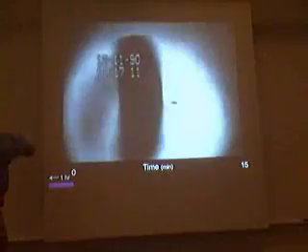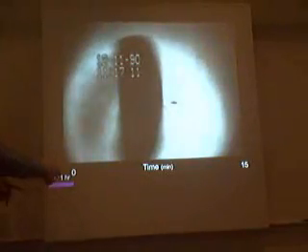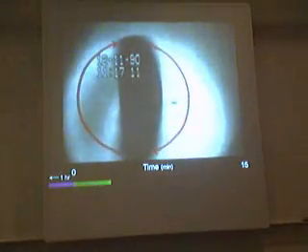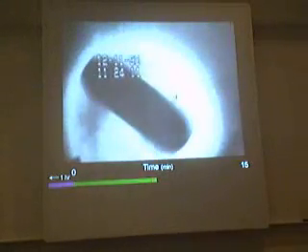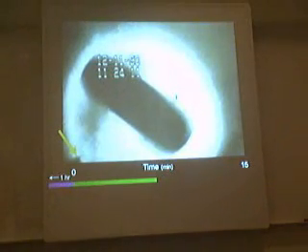We have a concentrated, supersaturated solution of sodium chlorate, stirring with a magnetic stirrer, a centimeter long. It's been stirring for an hour, nothing happening, so no point in showing you that. But I'll show you what happened during this 15-minute period. During the first 7 minutes, it stirs and stirs, nothing happens. But at the end of that 15 minutes, something is beginning to happen. You can see a crystal has formed down here, out of view, and it's growing slowly up in that direction, so you see the corner of the crystal. So we stir for another 7 minutes.